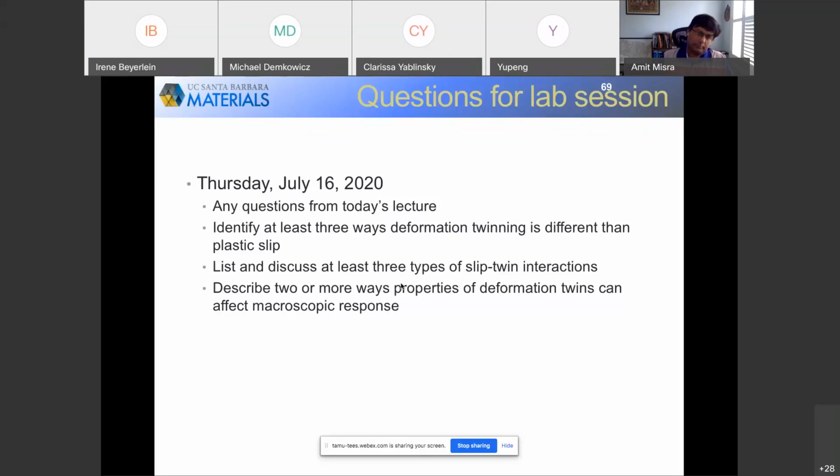As far as temperature, if the temperature is high enough that slip is favorable, and it can keep moving and is mobile and accommodating deformation the easiest way, there's no reason to transition to twinning. But if the temperature is not as favorable for slip, then it gives the opportunity for slip to become stagnant, to become slow, and then high rate or high stress dissociation processes could happen that could transition the slip to twinning.